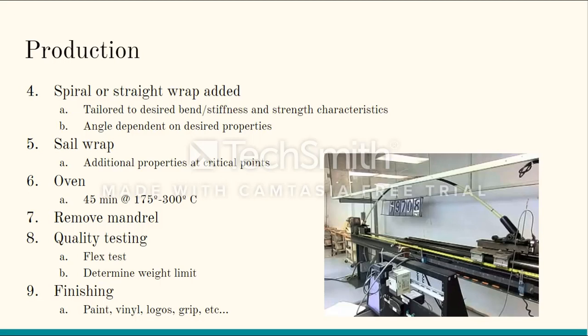Then a sail wrap is added, and this provides additional properties at critical points, such as extra strength at the bend point. Then the pole and the mandrel go into an oven, and this can either be steam or oil heated for about 45 minutes at 175 to 300 degrees Celsius.